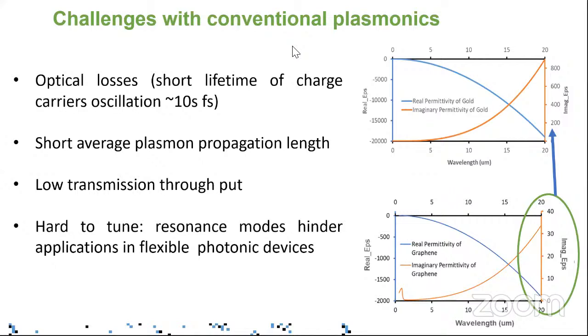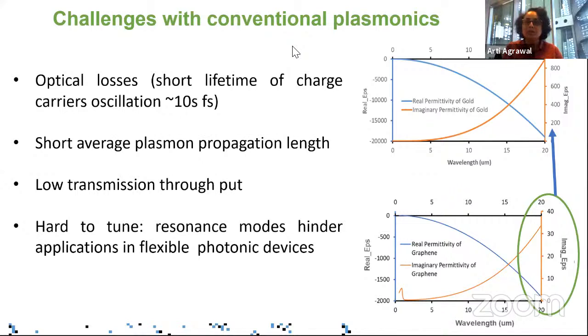So these losses in the conventional plasmonics using noble metals lead to large optical loss. And that's because of the short lifetime of charge carrier oscillations. Large losses also are linked to the short average plasmon propagation length. So you basically have an SPP that's created which cannot last very long and is highly lossy, which is counterproductive to what we are trying to do. So we cannot use these SPPs very effectively in metal-based conventional plasmonics. The other problem because of loss is that the transmission throughput of these SPPs is small, and they are also harder to tune. So even though we can get sub-diffraction confinement, we can't tune it, cannot use it as effectively as we would like. So there are different approaches that we can use, and that's what I'm going to talk about next.